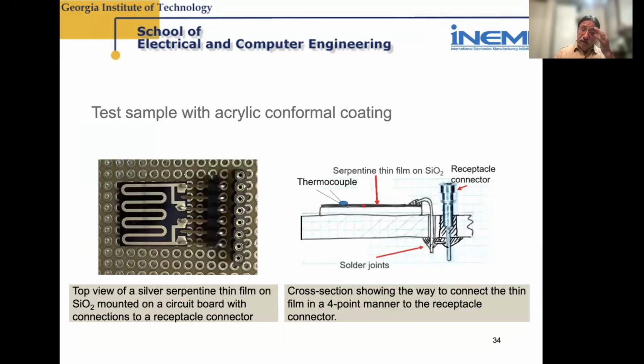So this work was done with a work group at iNEMI. Some test samples were made. So this is fairly large. This is many millimeters. So it has this serpentine metallization on SiO2. The whole thing is then mounted on PCB, and then it's coated with the conformal coating. In this case, acrylic, though we've studied other conformal coatings. So the question is, how thick is that coating as a function of position?